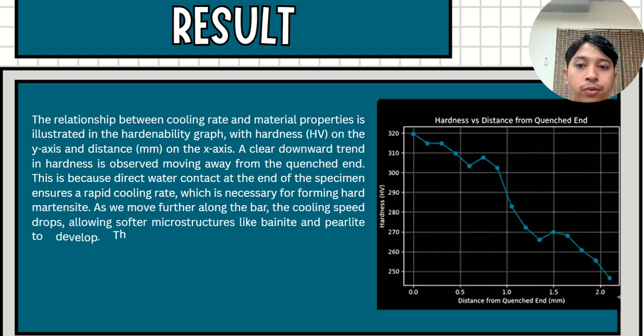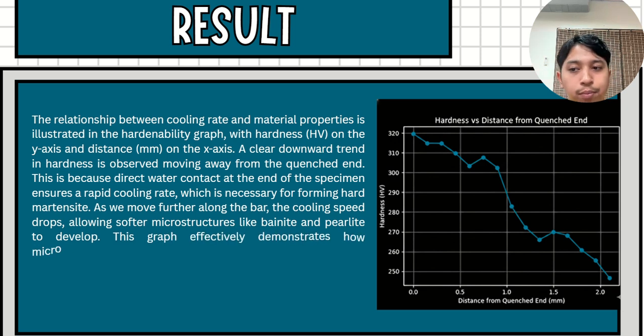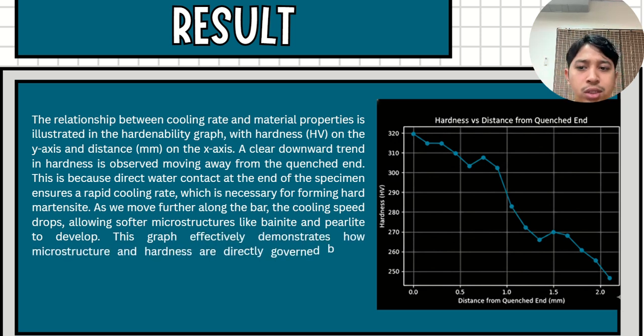The rapid cooling promotes the formation of hard martensitic microstructures, which is reflected in the peak hardness observed at this point. Moving further along the specimen, the cooling rate decreases, allowing the formation of softer microstructures such as bainite and pearlite, which correspond to the gradual reduction in hardness along the bar. Overall, this graph provides a clear visual representation of how cooling rate directly influences the microstructure and hardness of steel, highlighting the critical role of quenching in controlling mechanical properties.